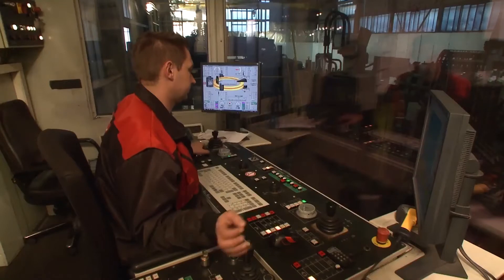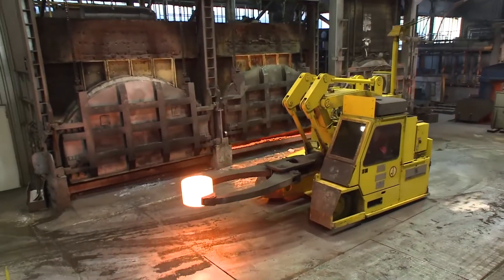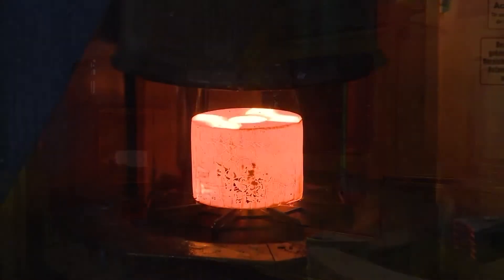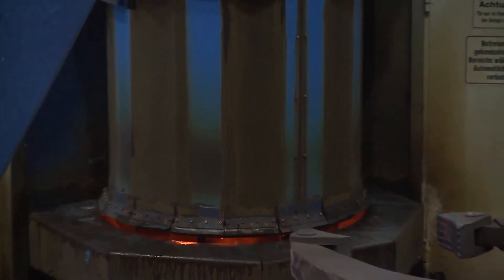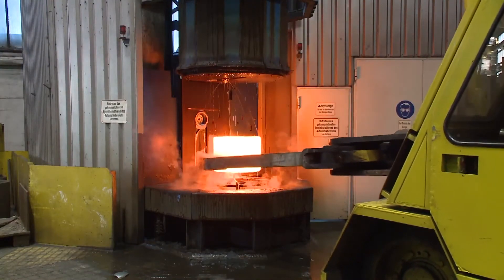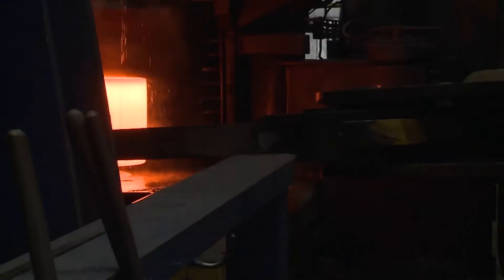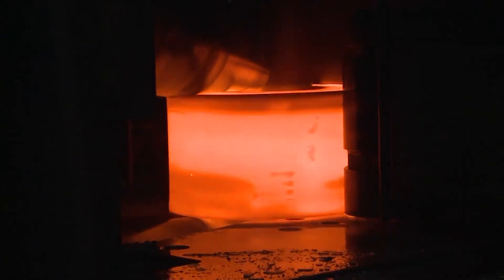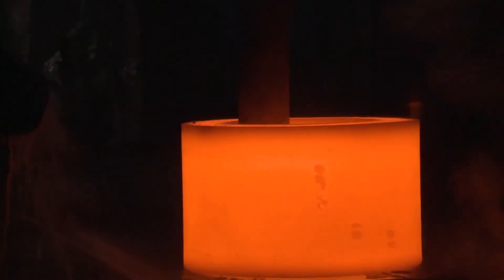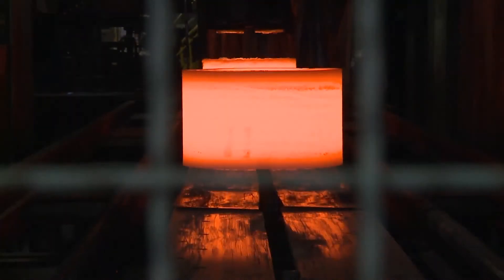Computer-controlled process monitoring provides visual information across the entire rolling path, displays the actual volume and, as a result, current dimensions, as well as any possible out-of-roundness of the rings. After being cleaned of residues fully automatically, the heated blanks are rolled seamlessly with tight tolerances by minimizing the use of material and reducing efforts and costs. The rolling forces of the axial and radial stand go up to 250 tons each, so that rings with outer diameters up to 3,500 millimeters, thicknesses of up to 850 millimeters, wall thicknesses of up to 500 millimeters, and weights of up to 8 tons can be rolled.